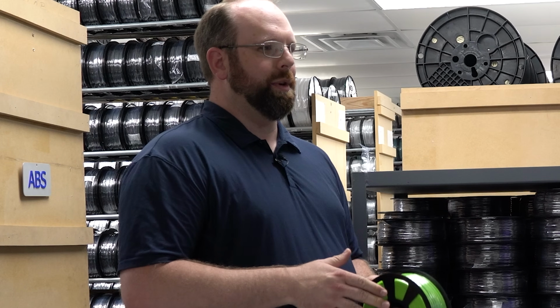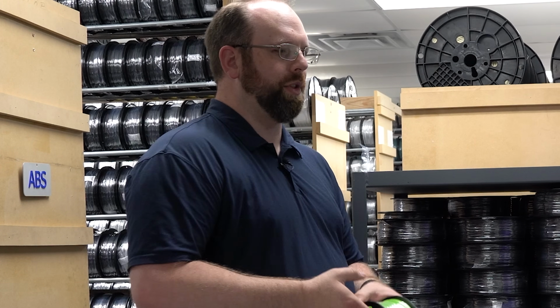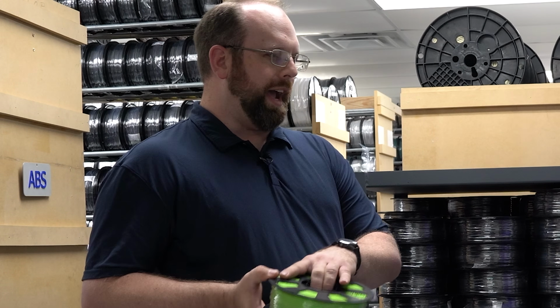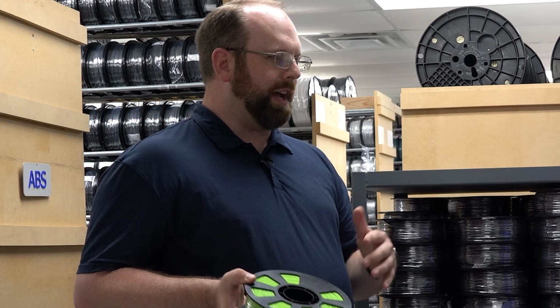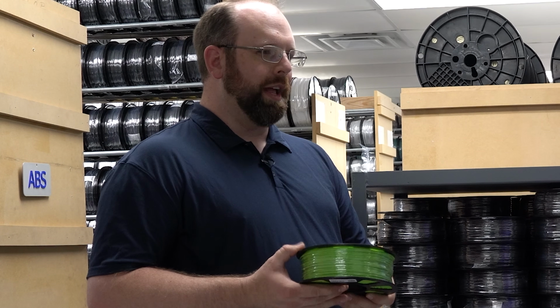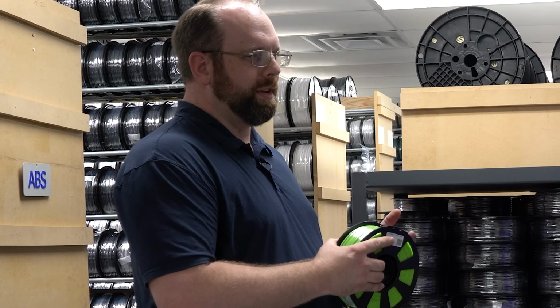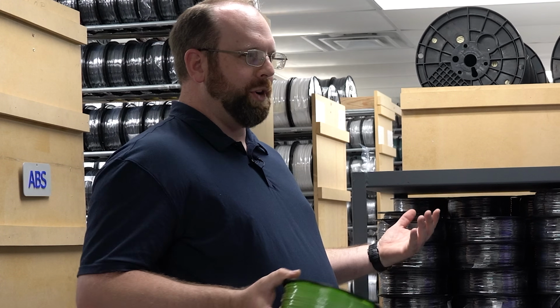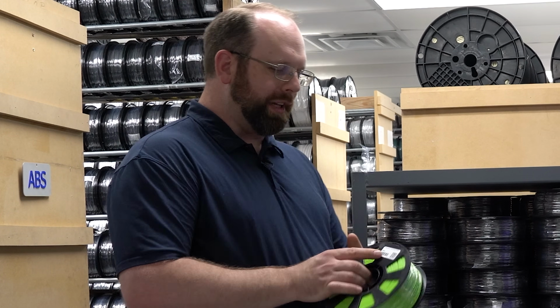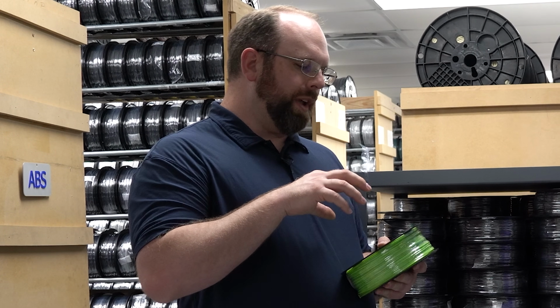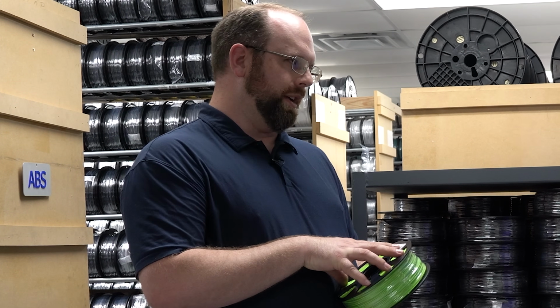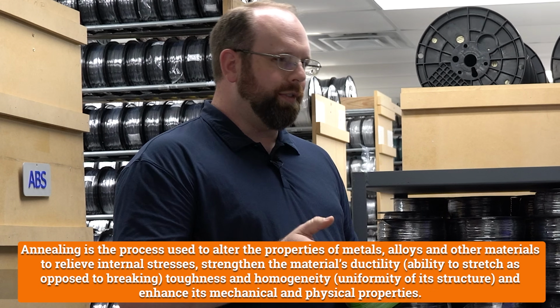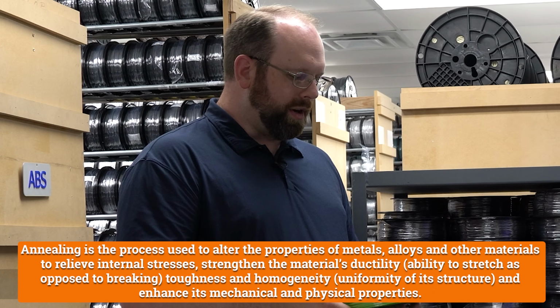So if you have an issue with your filament being brittle and then you throw it in a dryer at 60 C or thereabouts, the glass transition temperature of your material, and it's magically not brittle anymore, that wasn't moisture, because the moisture damage is irreversible. You just can't reverse it. And so what that typically is, though, is annealing. And that's where a lot of folks get a little confused, because annealing isn't a very common term.